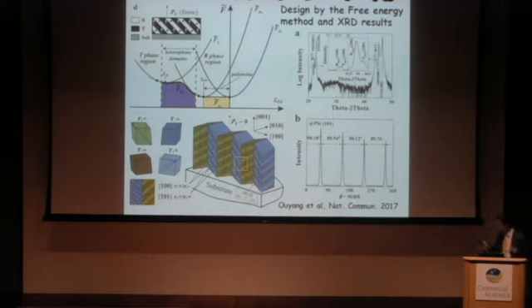Before I show you any experiment data, I just want to elaborate a little bit on my point here. You can see here, this is free energy as a function of misfit strain, right? I use the reference state as rhombohedral. You can see when there's no strain, the minimum is here. And this green curve is tetragonal. Of course, it's higher. The ground state is higher.